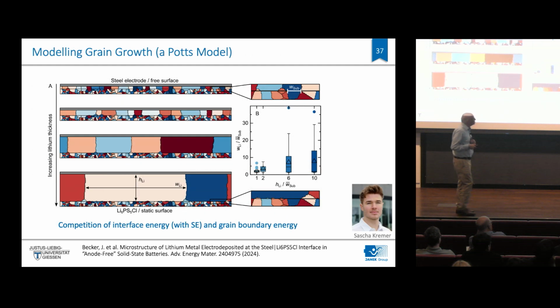And that is Sasha, some of you may know him, a PhD student in my lab who also spent some time in Kelsey's lab, and it's nicely cooperating. He made a little Potts-type model, which simply calculates the microstructure of such a film, where there are only very few parameters, and the two parameters are the interface energy with the substrate and the grain boundary energy. And if you do that with a two-parameter model, you can already get major elements of the film growth. So for me, the story is getting quite nice because we can already model a major part of the story.